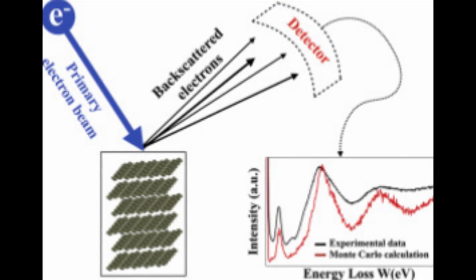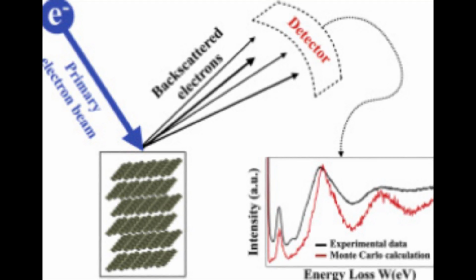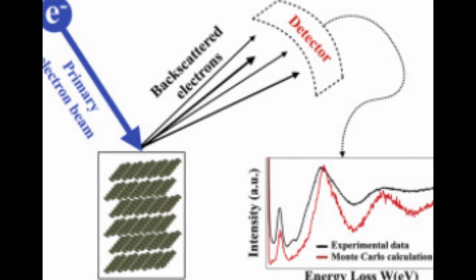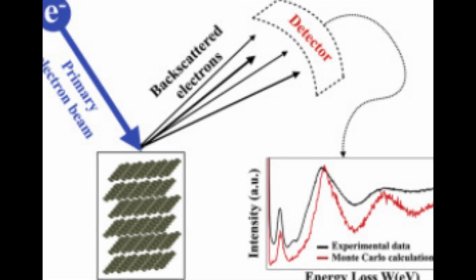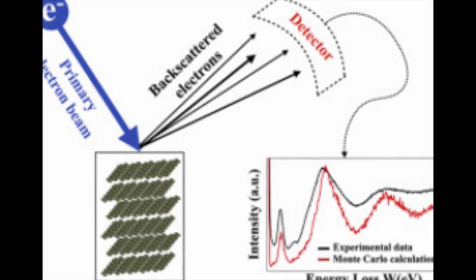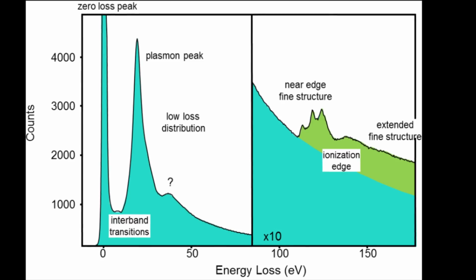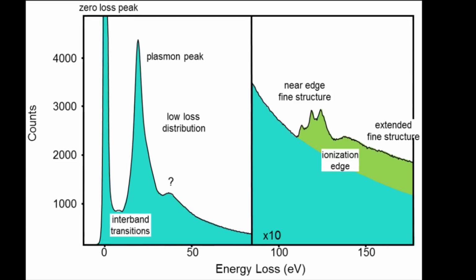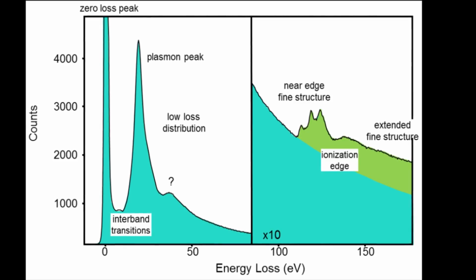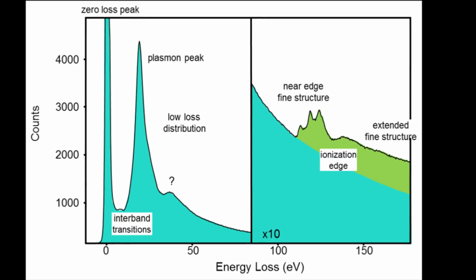The results of this experiment are summarized in graphics made using electron energy loss spectroscopy. Electron energy loss spectroscopy reveals the number of any particular type of atom by using a beam of electrons fired with a precise amount of energy. Some of these electrons lose energy after colliding with the sample material, a value that can be measured. By measuring and plotting this energy loss, the atomic composition of the sample material can be inferred. It was chosen for this experiment because of its relatively weak electron beam requirement, limiting the potential for sample damage.